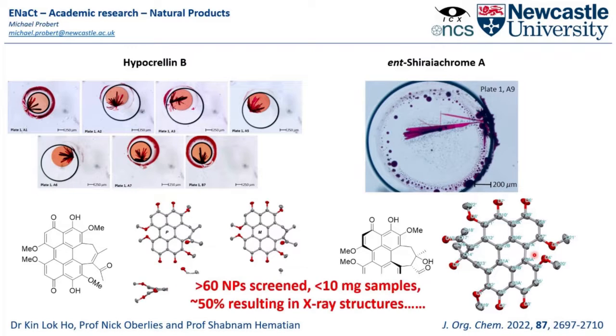But if we look at the total number of compounds we've analyzed, we've looked at around about 60 different natural products, each of which we generally have less than 10 milligrams of the material. That's essentially the world's supply. And about half of them, almost exactly actually, have resulted in full X-ray structure determination and mostly resolved stereochemistry. And this is a much higher hit rate than normally would be expected for the natural product research community. So that kind of demonstrates the broad range of compounds that you can approach. A lot of these natural products that we've looked at are much more flexible than the systems shown. It's just the ones that are shown are published.